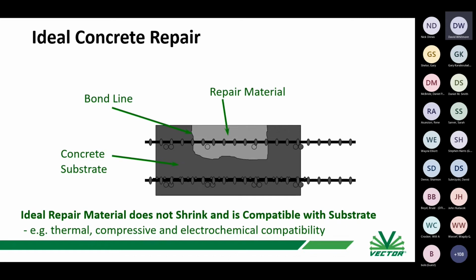And then we're going to talk primarily today about electrochemical compatibility, because if you're repairing with a piece of concrete that has no chlorides in it at all, and the rest of the concrete that's left is still somewhat contaminated with chlorides, then we're going to create some type of electrochemical incompatibility, i.e. voltage differences that are going to lead to corrosion starting the day you do that repair.